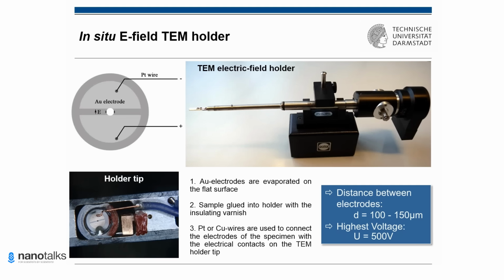Did you have any solutions to overcome some of these challenges you faced during your experimentation? Yes, for example, to increase the tilt possibility. What did we do? Firstly, we used a copper wire, which you can see in this image, around 230 micrometers. It was easier to glue, but of course the tilt range is reduced because it's harder and will not allow you to tilt to a higher angle. However, if you use platinum wires for contacts, which are around 50 micrometers, you will increase the tilt possibility.